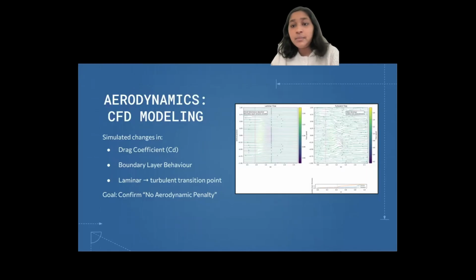This project required a multi-physics approach because aerodynamics, structural vibrations, and electromechanical conversion all interact with each other. I began with CFD simulations, which allowed me to quantify changes in drag coefficient, examine boundary layer behavior, and locate the laminar turbulent transition. For clarity, the boundary layer is the ultra-thin region of air, just a few millimeters thick, that clings to the wing surface and determines how smoothly momentum transfers from the surface to the free flow.